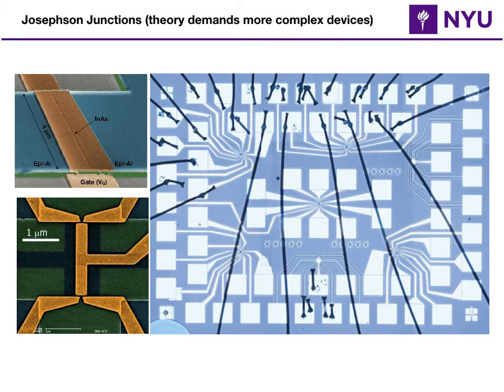And then we have a variety of these on a chip, and an optical image of it is shown on the right-hand side. So then you wire bond your favorite device and then you cool it down. So when we cool down a Josephson junction, usually the quality of the aluminum is really good because we grow the aluminum in MBE. It's high purity and there is a lot of control over its growth.